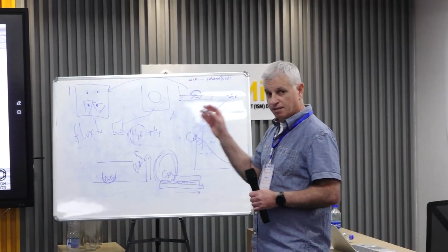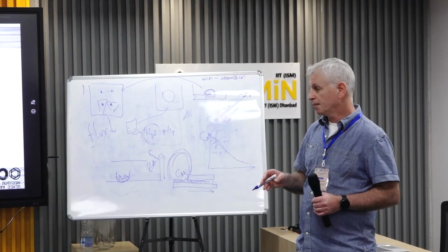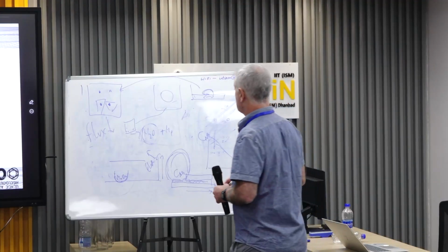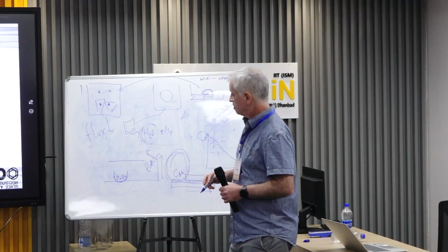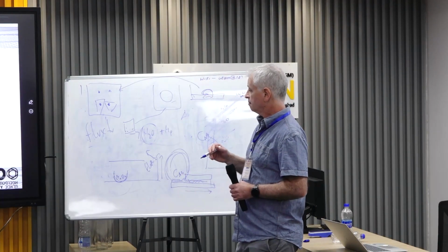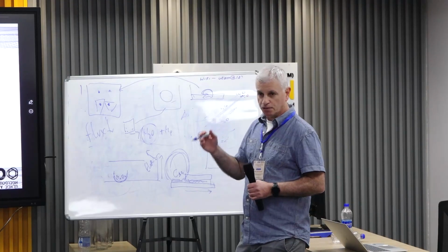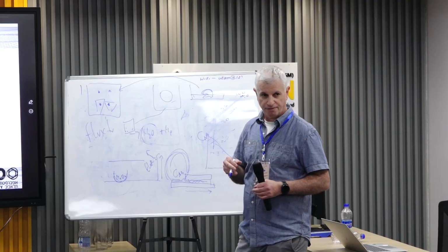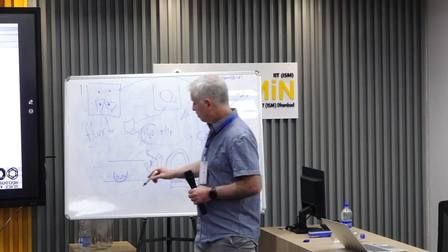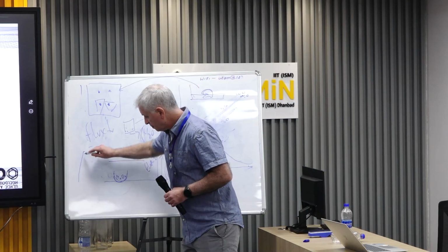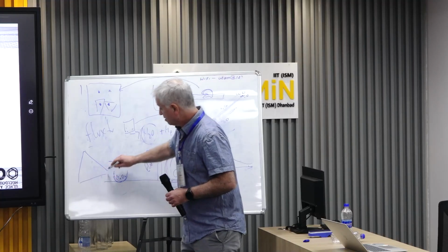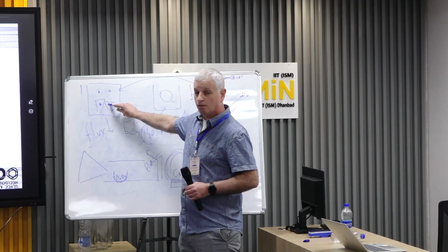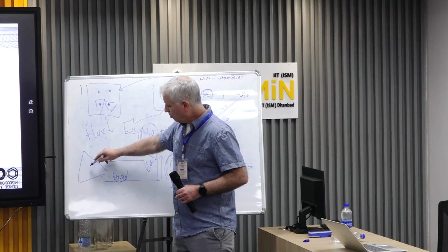So we thought this was a good method to start with. But the problem was that when we did it at high temperatures, I think above 850, what we got is surface diffusion of the gold on the TMD domain.